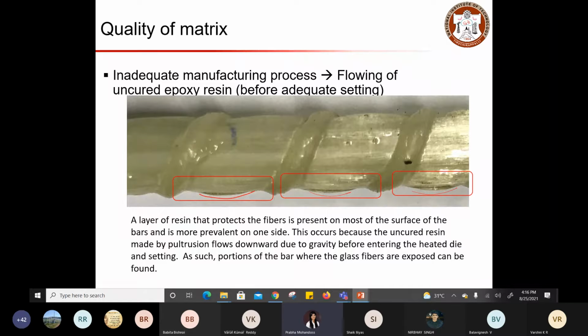Here these regions basically indicate how your epoxy got collected at the bottom due to the overflowing of uncured epoxy resin. So when you embed these fibers in epoxy resin, you give some time for its setting, right? While giving such time, you should ensure that the epoxy will adhere to the surface uniformly. If it is not done properly, and if your epoxy is overflowing on the surface, it will get accumulated at the bottom of your rebar, and you will observe this type of accumulation here. So a layer of resin that protects the fiber is present on most of the surface of the bars and is more prevalent on the sides.